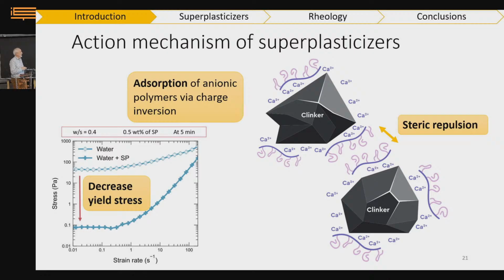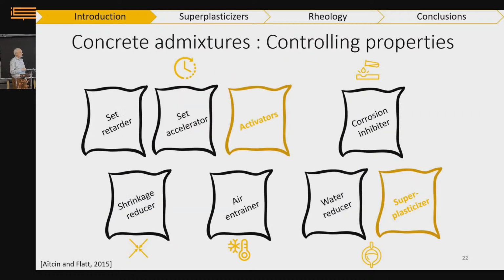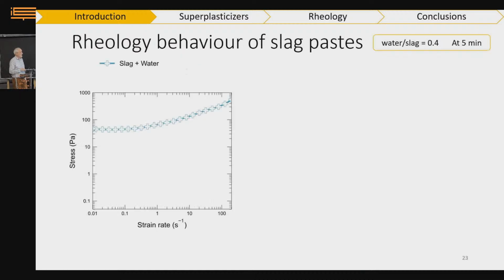If you take a suspension of slag in water, you have a yield stress, and if you add superplasticizers to it, you decrease the yield stress. Okay, so those superplasticizers are efficient with respect to slag, just as with clinker. The problem is that we have to combine them with the activation, because the slag in itself is not reacting. And that's when the trouble starts. This is illustrated in this figure here.